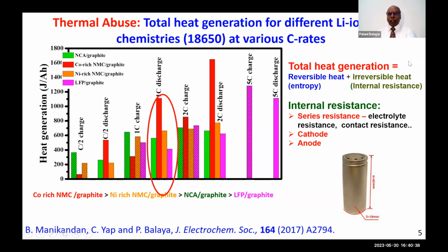Now, please take note of the message here. The total heat generation, whatever you measured, is because of two reasons. One is reversible heat because of the entropy changes when you remove lithium and then when you put back lithium. This is chemistry specific. We have absolutely no hold on that. But there is so-called irreversible heat loss due to the internal resistance. That internal resistance could be because of the electrolyte, contact resistance, or what is happening on the positive electrode, what is happening on the negative electrode. So I'm going into the details of the irreversible heat loss, which we can have some control over. As I said, reversible heat loss is chemistry specific. We have absolutely no control on that.